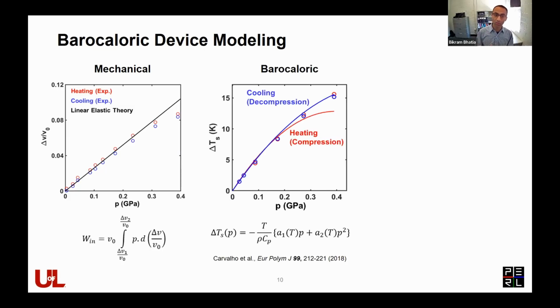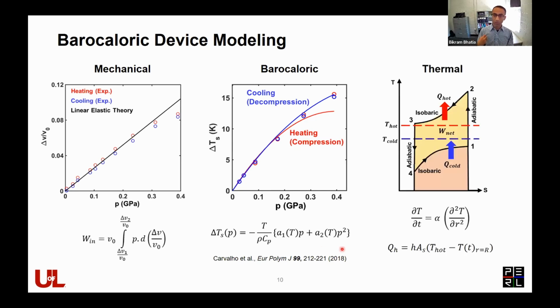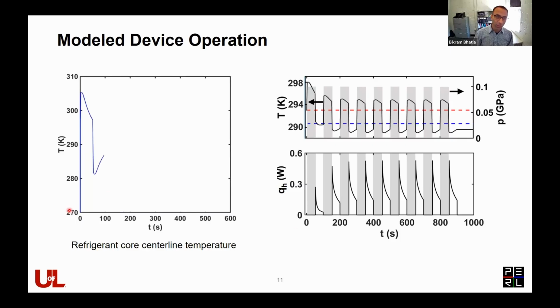Then we have the barocaloric response of the material. So how much does the temperature of the material change with applied pressure? Again, for this, we mostly use some phenomenological work that is reported in the literature, and also experimental data reported in the literature for elastomers, which do not have a phase transition. And we model the thermal transport, as heat goes into the refrigerant and out from the refrigerant, using basic heat conduction and convection equations. So we have this finite difference model, which can basically numerically model the operation of the heat pump. So we can predict what the temperature cycles will look like for the refrigerant, and also for different hot and cold thermal reservoirs, and also predict how much heat is being delivered in each cycle at every time step.